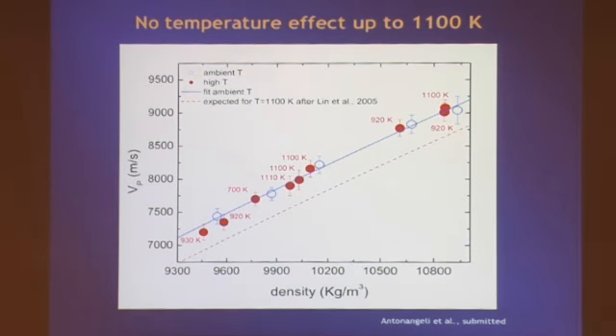And here are the results that, once plotted as a function of density, follow the same trend as those indicated by ambient temperature result. And this is irrespective of the temperature, thus suggesting that non-harmonic high temperature effects are negligible at least up to 1100 K, and that VP scales linearly with density irrespective of the specific pressure and temperature condition. The softening expected from the work of Lin and co-workers, which I was not able to show you before, I just described, suggests a softening along this line. And as you can see, that is quite far off, even considering error bars and even at the lowest compression, where anharmonic effects are expected to be more relevant.